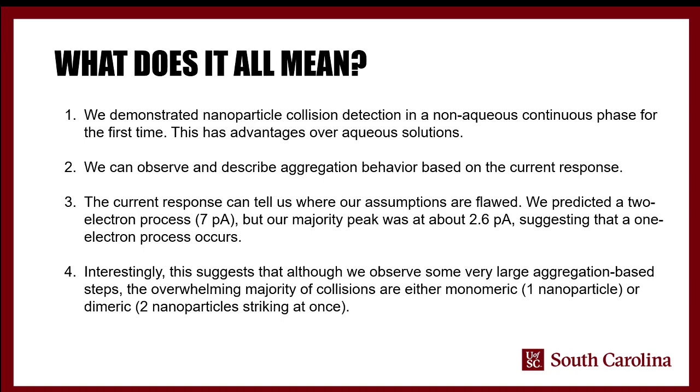We were able to observe and describe aggregation behavior based on the current response, so we could just total up all the current steps and observe the large steps and tell that there was some kind of aggregation going on. As I said, the current response actually tells us that our assumptions were flawed. We can be reasonably confident in the diffusion coefficient. We know what the concentration of both our nanoparticles and our probe molecules were, but one of the big assumptions that we made was that the oxidation of tripropylamine was going to be a 2-electron process, which should have given us a step size of about 7.